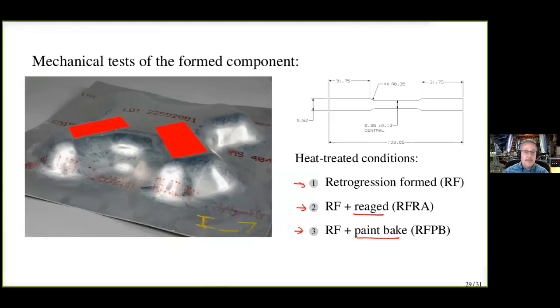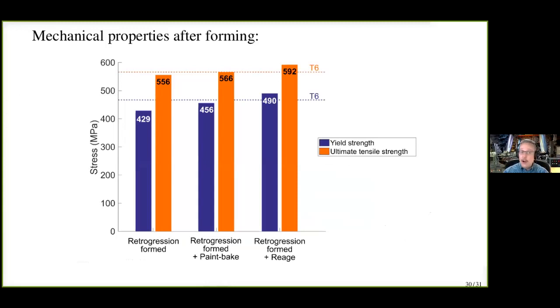What do we get out of it? Well, here are results. Now this sheet is actually a 7075 alclad, which means it has a thin layer on top and bottom of low alloy aluminum, which helps to protect from corrosion. And this was the UTS, ultimate tensile strength, of that material in the T6 condition. And then this is the yield strength in that condition before we formed it at all.